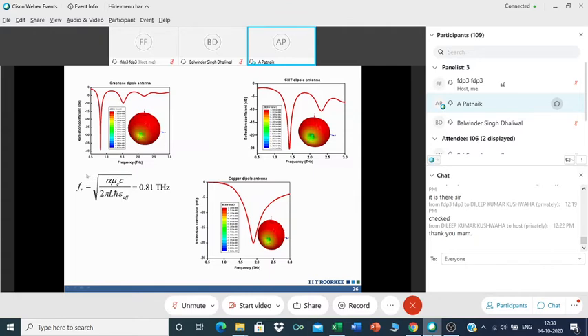Or you can say that the compactness of these graphene antennas at terahertz frequency is much better. You can get a very compact graphene antenna compared to CNT and copper. So once we found that graphene is giving better performance, then we tried to find out its resonant frequency.